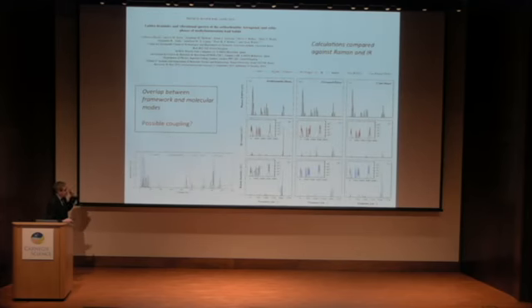That theme has appeared time and time again in the literature. This is a paper that was published again fairly recently, I think just in November or December of 2015, where they do a series of calculations and some Raman measurements on the iodine version, and they suggest that there is a strong coupling between the molecular site and the host framework lattice. So basically what they're saying is that there's a fairly strong coupling between the methyl ammonium molecule and the lead iodide framework. And they tie that to the electronic properties.